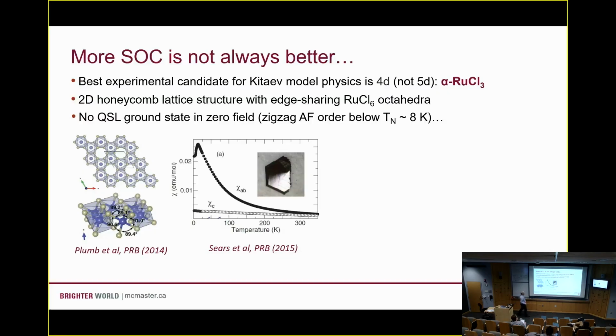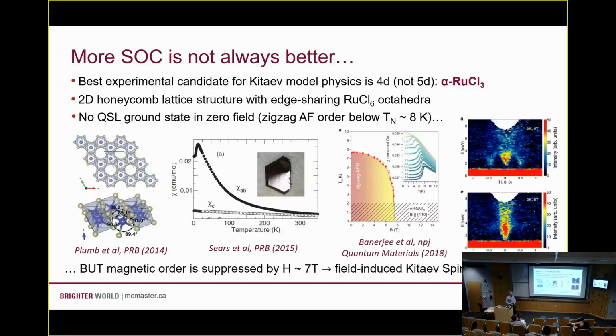It does order at low temperatures, but it is quite close to what we think of as this quantum spin liquid regime. And if you apply a 7 Tesla magnetic field, you can kill off this ordered state, and you get into what has been proposed as this field-induced Kitaev spin liquid regime.